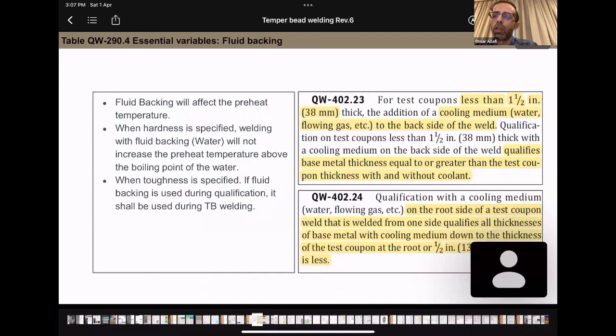It's quite interesting that this effect might work fine for hardness, but it's exactly the opposite for toughness. For hardness, the preheat temperature, for example, will control the hardness and result in a better hardness value. So the higher the preheat temperature, the lower the hardness value in the heat affected zone. But this is not the case when it comes to toughness. Toughness will be adversely impacted by the preheat temperature.